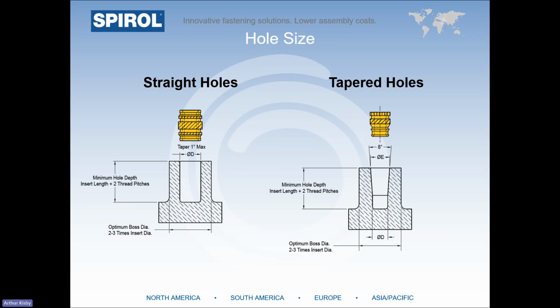The hole size an insert gets installed into is also critical for the insert's ability to perform in the assembly. For inserts that are used in straight holes, it's recommended that the taper doesn't exceed 1 degree inclusive, or a half a degree per side. For inserts intended to be used in a tapered hole, we recommend the taper to be 8 degrees, or 4 degrees per side. Using an insert designed for a tapered hole assists with removal of the plastic component from the mold, but also allows the insert to sit deeper into the hole prior to the installation, facilitating square and faster installation.